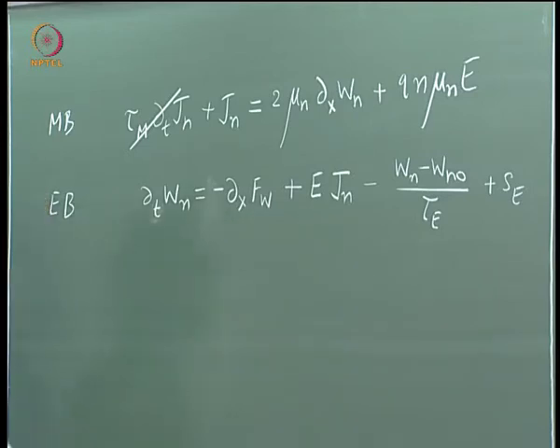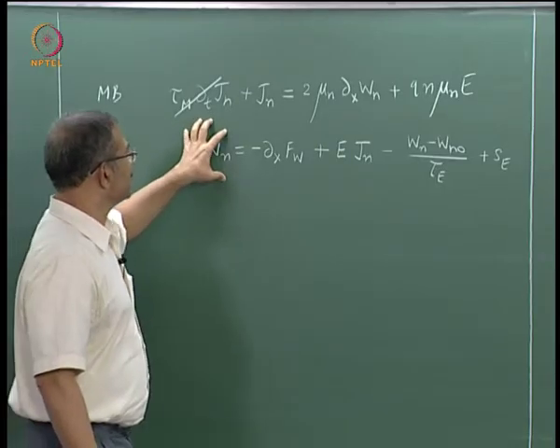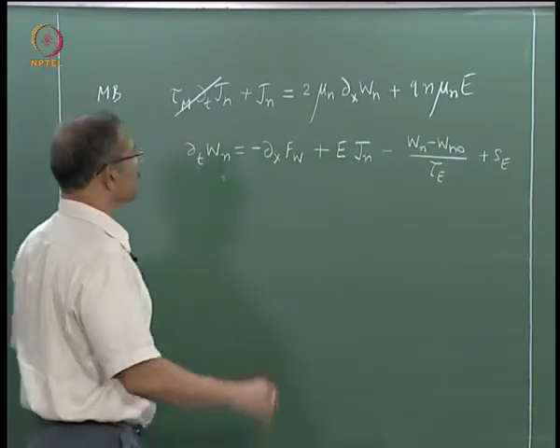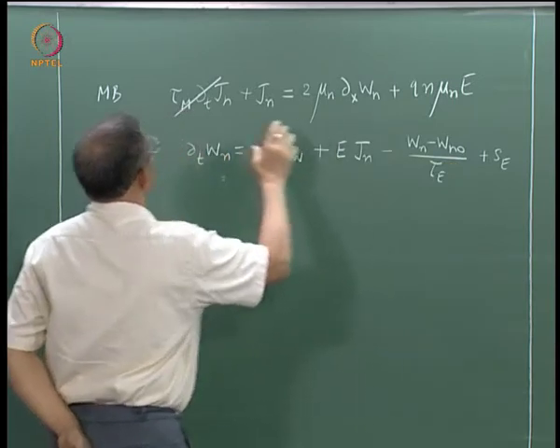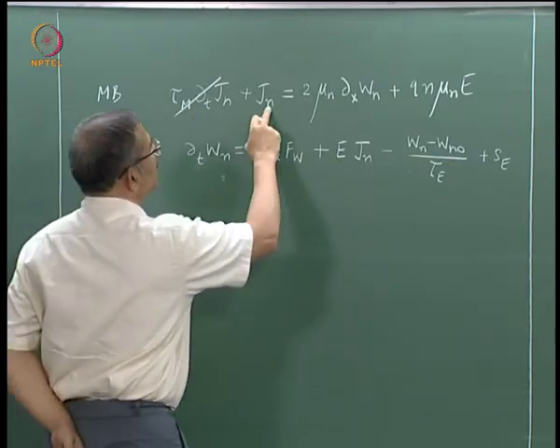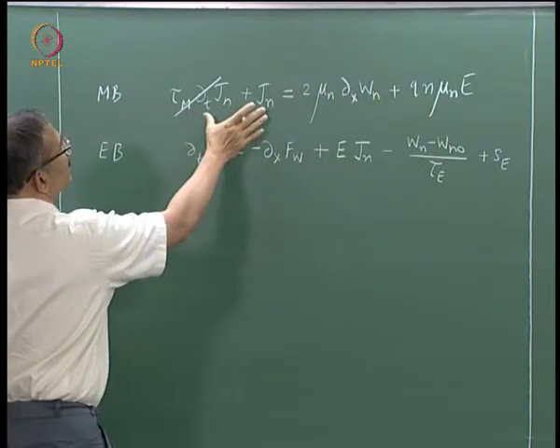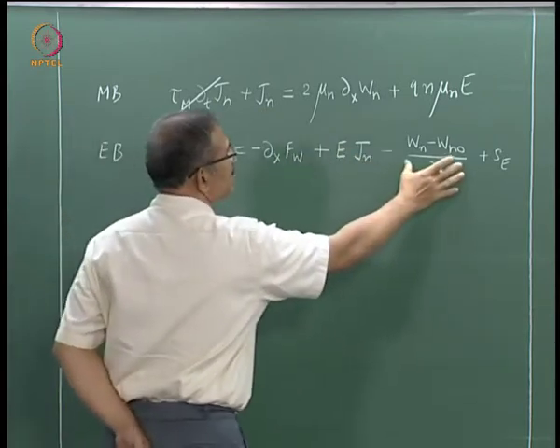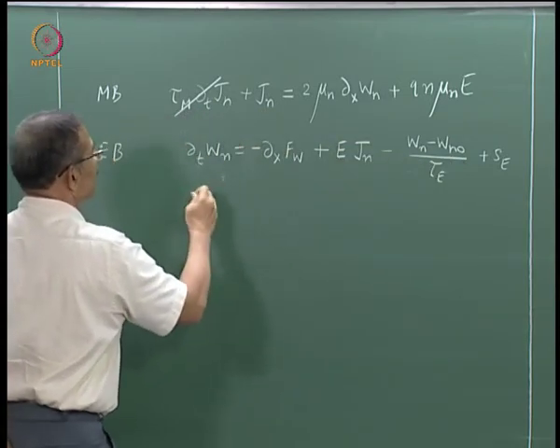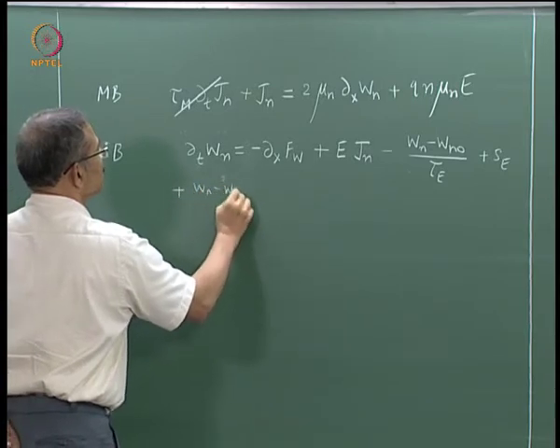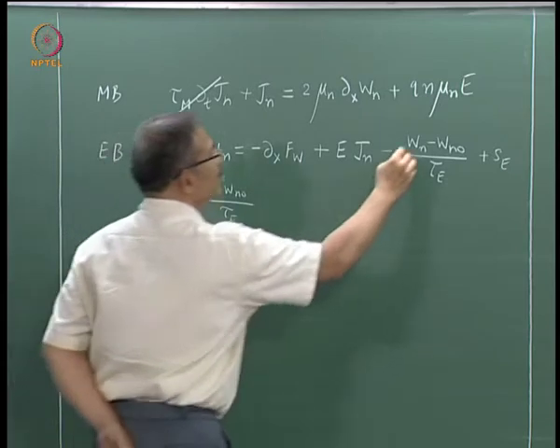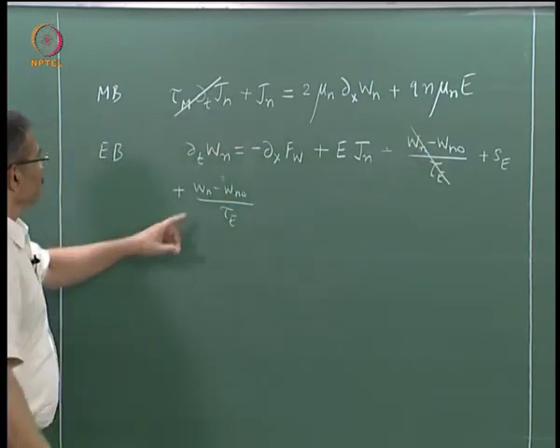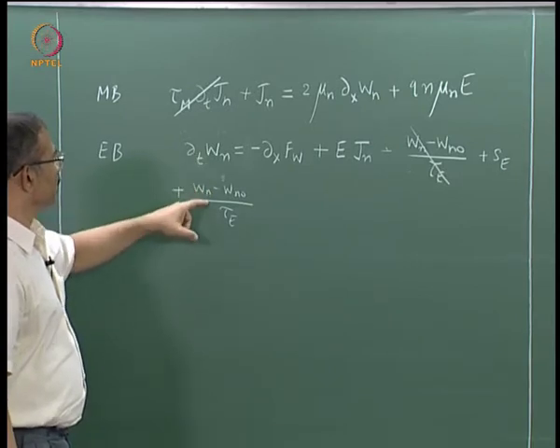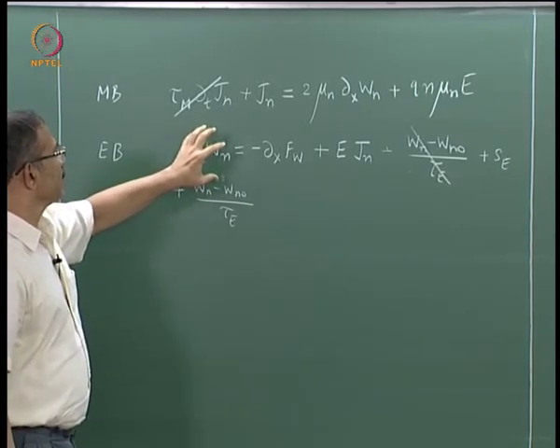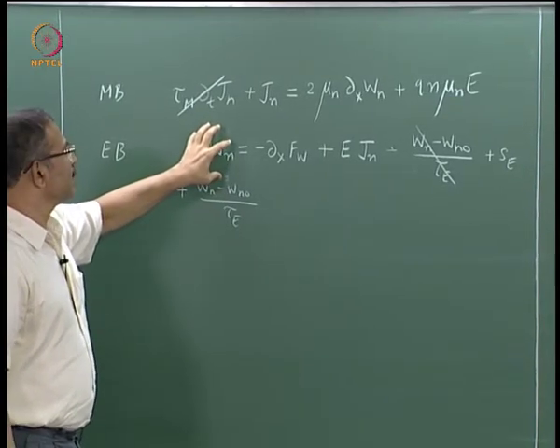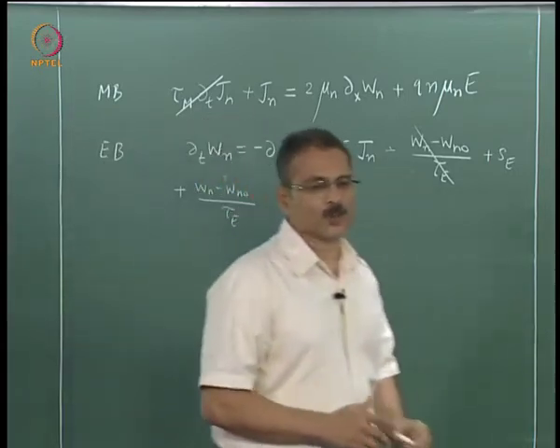Now returning to this energy balance equation, we want to neglect this term, so we would like to compare this term with any of the terms here. One term that you can compare it with is this. Just like for the momentum balance equation, we moved this Jn term from the right hand side to the left hand side, and that allowed us to compare these two terms. We can move this term to the left hand side, and then it will appear as plus Wn minus Wn0 by tau e. Now we can compare these two, and if this is very small compared to this, then you say that the quasi-static approximation or steady state approximation for kinetic energy is applicable. So that is what we have done here.